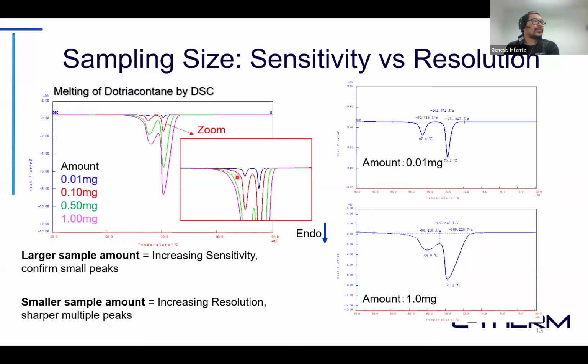So from blue to purple is the increasing amount of sample used when testing. It makes sense that you have really small signals when you're using really small amounts, but you can see here that the peaks are really distinct from one another. So again, you can see it from here. And as you increase the amount of the sample, the peaks start overlapping one another. So what you get is information such as, oh, we get two peaks right here for sure.